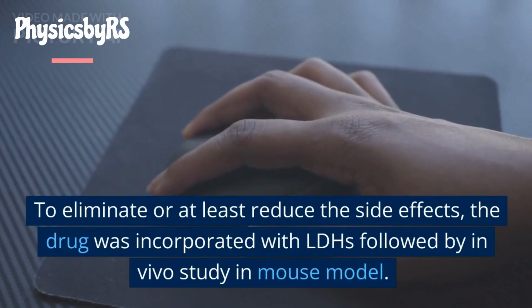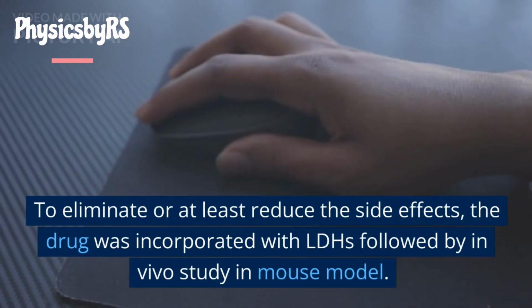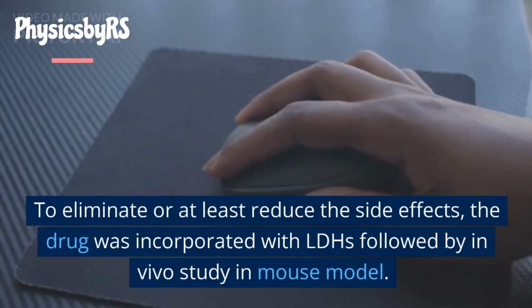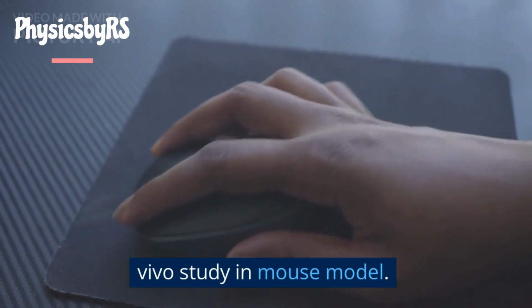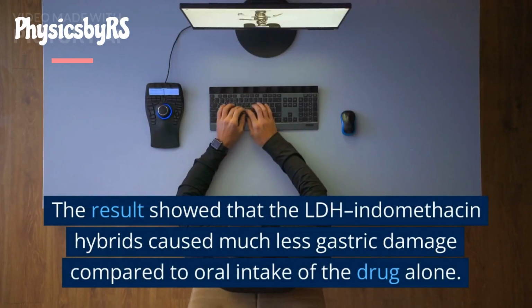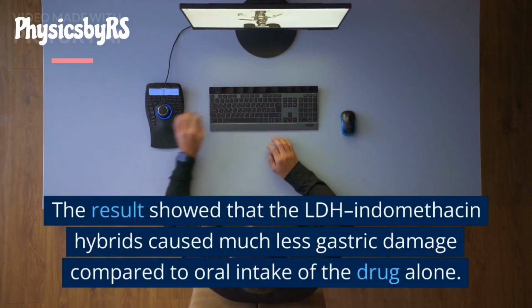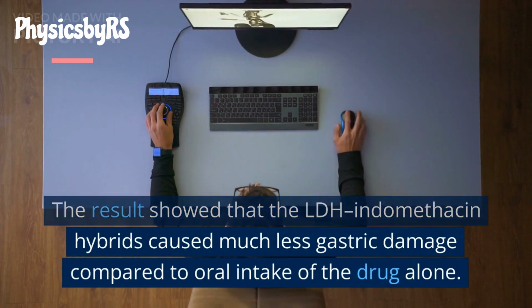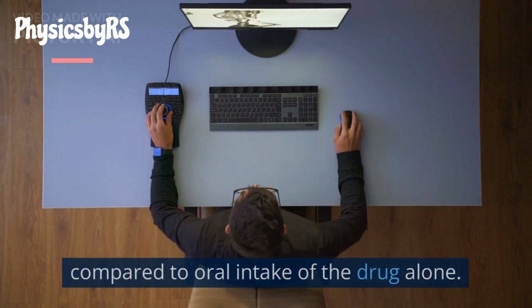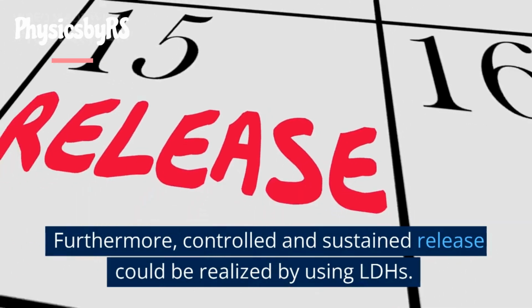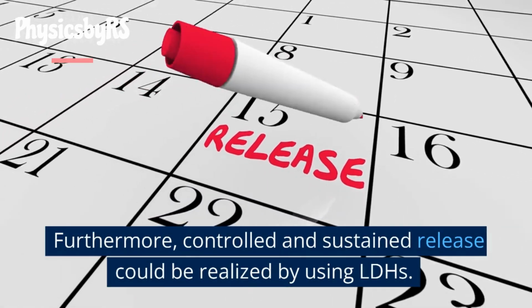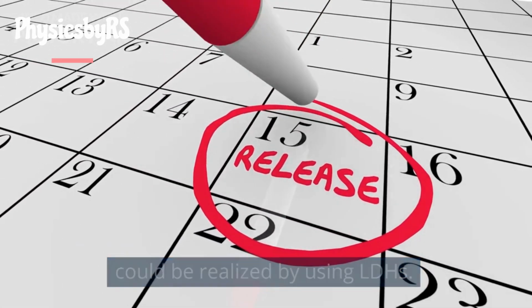To eliminate or at least reduce the side effects, the drug was incorporated with LDHs followed by in vivo study in mouse model. The results showed that the LDH indomethacin hybrids caused much less gastric damage compared to oral intake of the drug alone. Furthermore, controlled and sustained release could be realized by using LDHs.